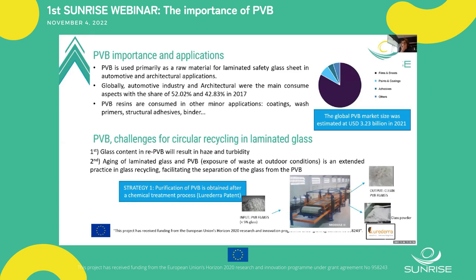So if we go to the first and second challenges we identified, in this project we have two major strategies. The first strategy goes to the purification of PVB in order to clean the glass from the PVB. In this case, Lurederra worked in the past and has a patent for the purification of this PVB with a chemical treatment. This chemical treatment follows the mechanical treatment and obtains clean PVB flakes, so avoiding this glass problem, and also avoiding the preliminary degradation by the recyclers in order to separate the PVB from the glass.